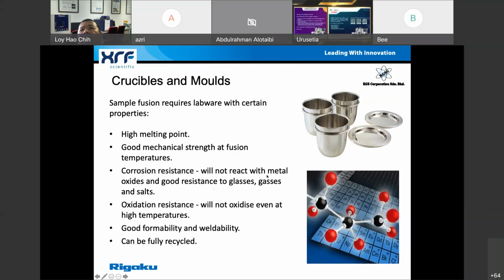Okay, corrosion resistance is with metal oxide. That's why during the fusion process, you must ensure that all your samples have already been converted into oxide form. So that means you don't put raw metals inside your platinum crucibles, and try to avoid your platinum's contact with